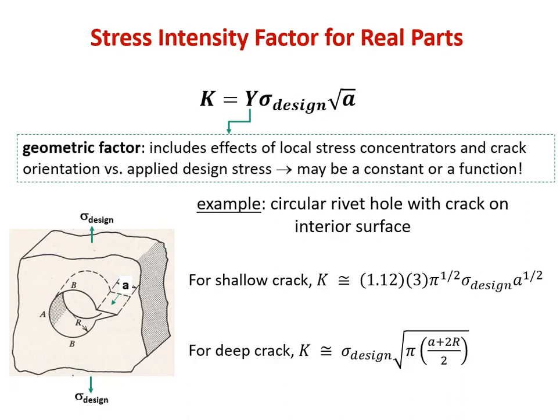If the crack got deeper, you would have a completely different expression for Y. And in this case, you would roll your square root dependence of a in with Y, and you would end up having the expression there for a deep crack. And that is, again, just for that particular geometry. You will have a different Y for every specific different combination of crack or flaw geometry relative to loading.